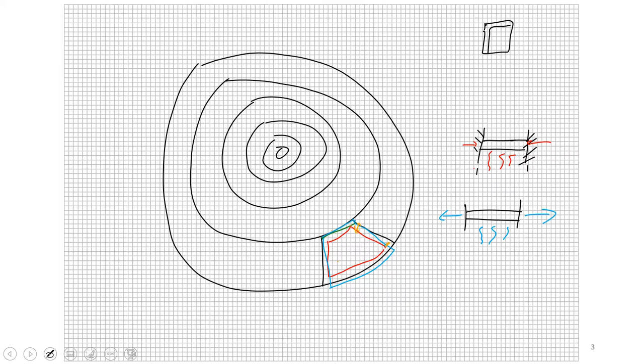And then because of the difference between the outer surface, where there's a lot of shrinkage, and the inner surface, where there's very little shrinkage, you get differential movement, or more precisely, you get constrained stresses. So what ends up happening is you get tensile stresses, kind of like this. And you get them because drying is not a perfectly uniform process. I drew this as happening kind of like a wedge, but in reality it's sort of a continuous process going all the way through the tree trunk.